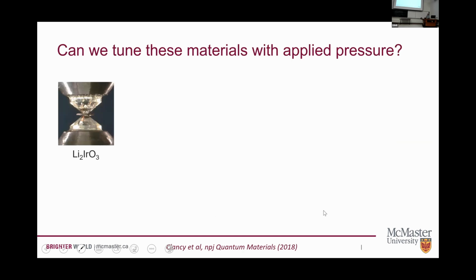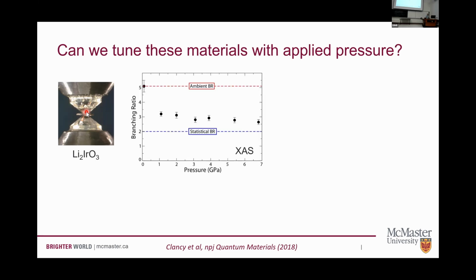I won't spend too much time on this except to say that there are many different ways that we can tune these systems to try and get them closer to this Kitaev limit. Pressure was one of the first that we looked at. So if you put these materials inside a diamond anvil cell, you can crush them to very high pressures, sort of 1 to 20 gigapascals, so many thousands of times greater than atmospheric pressure. What do we see when we do this? Well, we see the branching ratio responds. It's very sensitive to applied pressure, okay, drops off very quickly.